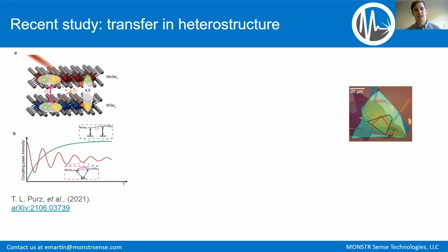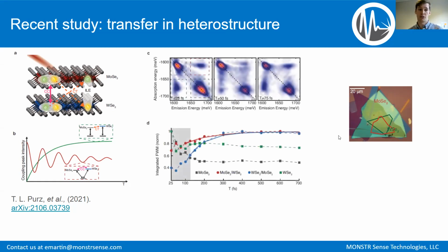And in here, it's common to look at, with photoluminescence, this interlayer exciton, which is these 2 layers, these 2 monolayers put right next to each other, electron in one, hole in the other layer, and they can bind to form an interlayer exciton. This has been measured with photoluminescence, but there's actually another type of interaction between these 2 layers called coherent coupling, where you have an exciton in each layer that interact through dipole-dipole interaction. These can be distinguished using 2D spectroscopy.